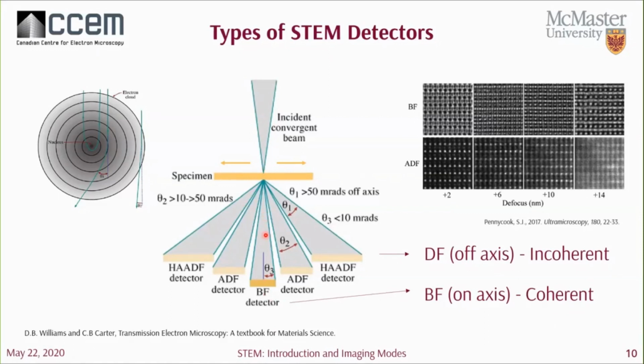These bright field detectors produce images that are quite similar to coherent bright field TEM images, shown here in this top row, with one advantage being that we can get an image that isn't subject to aberrations from the image forming lenses as we would use in the parallel beam mode. It is interesting to note that we still see contrast reversal going through focus, so here versus here, which is a factor resulting from the coherent imaging.